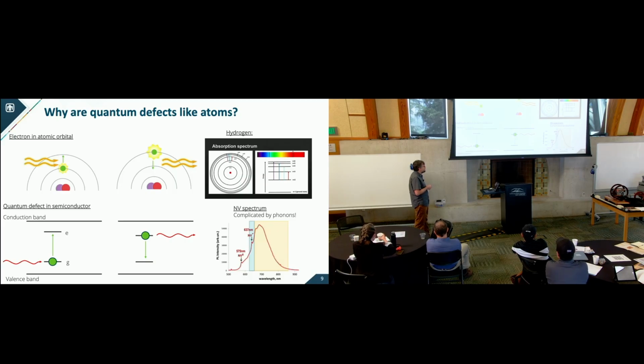But it gets a bit more complicated because you're in the solid state and you have phonons everywhere, so quantized lattice vibrations. And so in that case, instead of having these sharp emission lines like hydrogen, you only have one what we call zero phonon line, right, and a huge phonon sideband, particularly for the NV. So this is the direct energy levels here, and all of this are quantized phonons. So you can actually emit lower energy photons because you're also emitting a phonon at the same time. And I'll show you a picture of that here in a second.